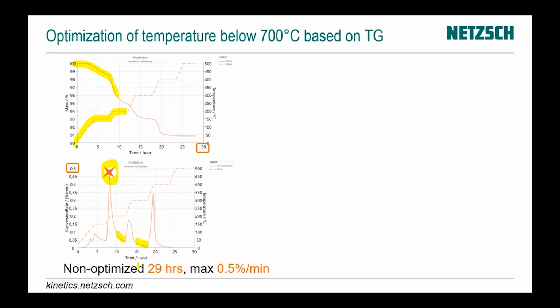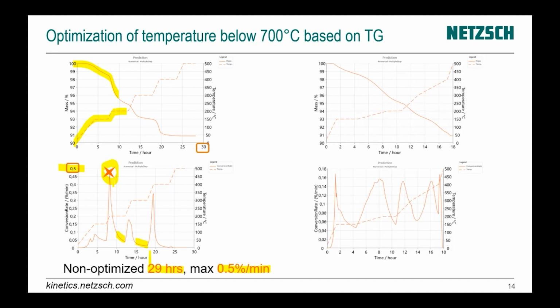And here, for the non-optimized process, we have 29 hours and 0.5% per minute. Here is the maximum decomposition rate. After optimization of this process inside our software, we can make it a little bit slower in this range and a little bit faster in the range with a slow decomposition. And here is our result. We have an optimized 18 hours, maximum 0.16% per minute. So here the maximum decomposition rate is almost 3 times less.